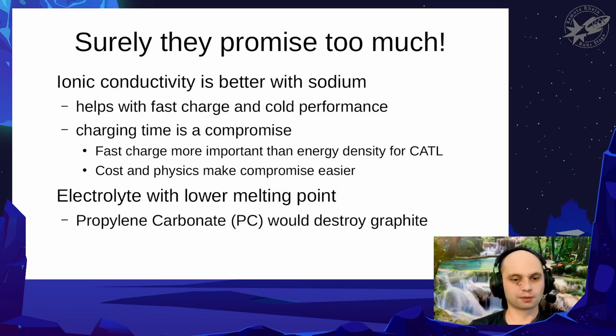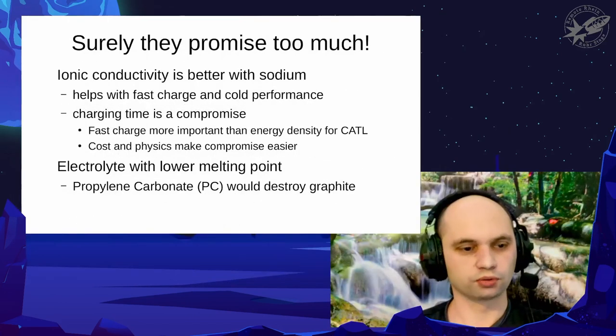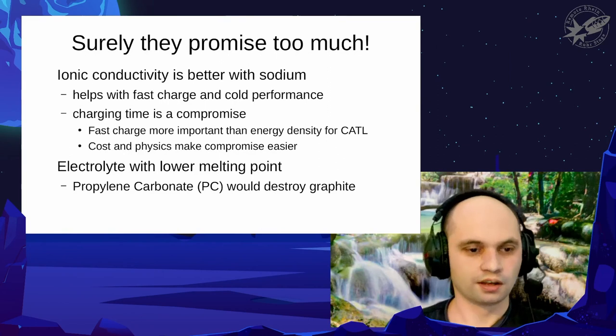The other point that people looked at and were incredulous about is, well, they must be promising too much. The battery is charging so fast. It works better in the cold. How is that possible? And the point is, sodium doesn't react so easily with all the stuff around it, so the sodium ions can flow easier through the electrolyte, and you get higher ionic conductivity in the same kind of electrolyte, and you use the same kinds of electrolytes. That's how you can charge them faster.